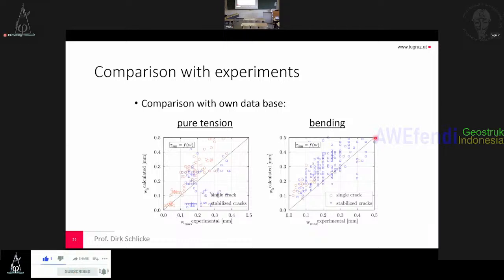Otherwise, we must run calculations with scatter of tensile strength, and then you need random field theory, for example, like a Monte Carlo simulation, and this would, I would say, from computational time, last over a couple of years. This is almost impossible. But this is the reason: we compare experimental data, which does not necessarily give you the theoretically maximum crack width, with a calculation which shows you the maximum crack width. Thank you, Farid, for the question.